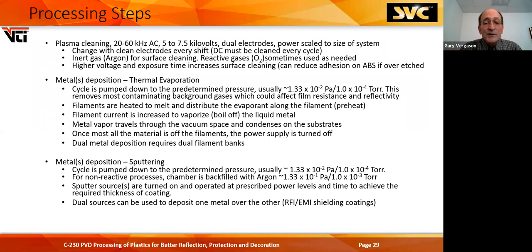Usually argon gas is used to clean the surface. You can use reactive gases like oxygen if you need additional cleaning to take place. Higher voltages and longer exposure time increase your surface cleaning. But in the case of ABS plastic, you can actually pull the rubber to the surface and give yourself greater adhesion problems by over etching. Then you deposit the metal.